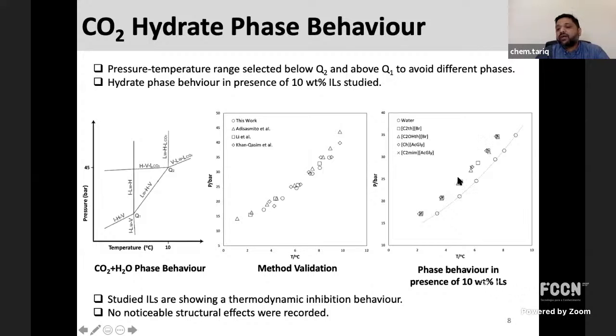And then in presence of 10 weight% ionic liquids, what we found is that all ionic liquids are shifting this hydrate equilibrium towards lower temperature and higher pressure. But what is interesting here is that we cannot distinguish which ionic liquid is working better or which is worst.